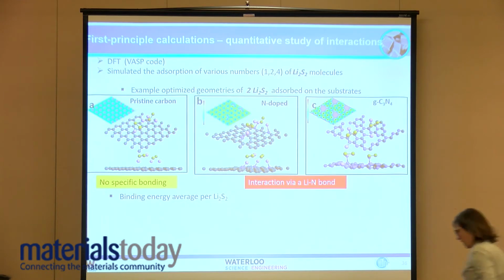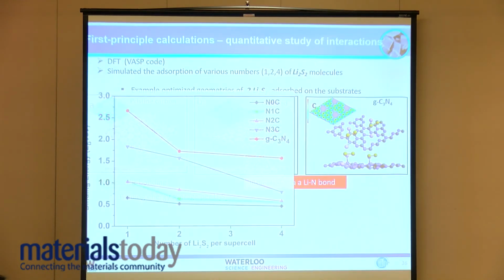Okay, so we have no specific bonding. And so if you take a look at the results of these calculations with just carbon, with one nitrogen, with two nitrogens, and all the way to the carbonitride, you see that there is much greater interaction once you get up to the graphitic carbonitride. So then it was a matter of figuring out how to combine that, because it's an insulator, with graphene, which we did by literally exfoliating both and packing them back together again.